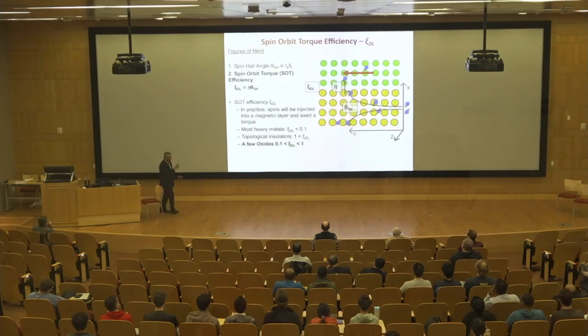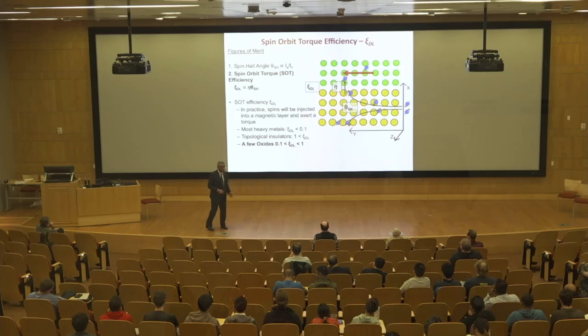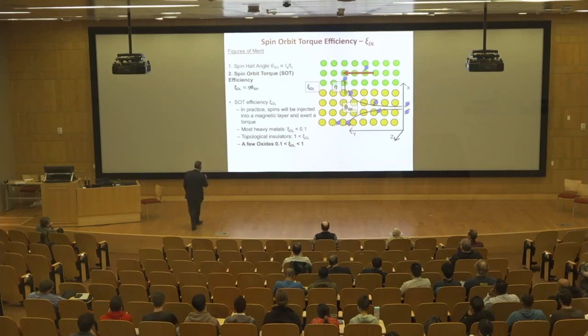Sorry about some of this stuff, but it's just the pedagogy behind the spin-to-charge conversion. If you have a ferromagnet which is connected to a material, it turns out that the efficiency of this conversion between a spin to a charge is measured by something called the spin Hall angle, which is given the notation theta. It is the ratio of the spin current to the charge current. Okay? And the spin-orbit torque efficiency, xi, is just the interface transparency, which is typically around 1, times this theta value.